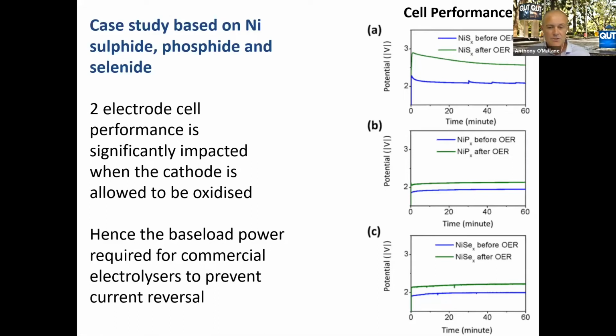But then if we switch electrodes, or actually turn it off and then turn it back on again, we can see that the voltage goes right up for all of these materials. Again, that's being influenced by the chemistry happening at the cathode if it's allowed to be oxidized. So it has quite a detrimental impact on the overall cell potential if we allow that to happen.